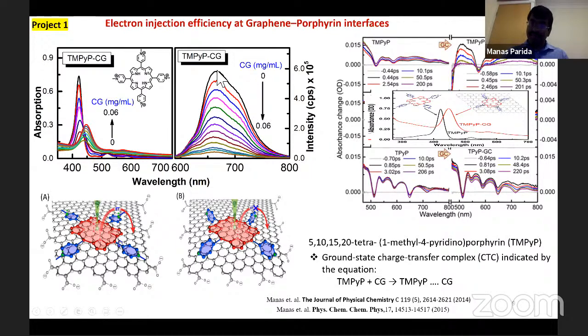When the emission peak systematically decreases, we say the emission is quenched. That means the emission has gone; it is not emitting as much now. That makes sense because it is no longer only porphyrin, but a combination of porphyrin and graphene. With the shifting as an indication, they have a very good interaction. The term they use is that a complex forms between graphene and porphyrin. Due to electrostatic interaction, they are very close and affect each other. There is a pi-pi interaction, so the molecules stay together as you see in the figure. Then the electron inside will be transferred to graphene.